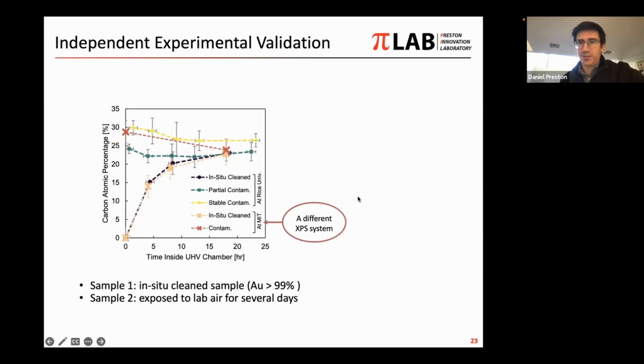But we wanted to make sure that it was not just our system. And so we worked with a different system. This system was at MIT. It was an XPS chamber in which we could measure the carbon percentage over time. And we had a couple of samples. So in this light, almost salmon color, we had an in situ clean sample in the MIT XPS chamber. And this mirrored almost exactly our results obtained at Rice.